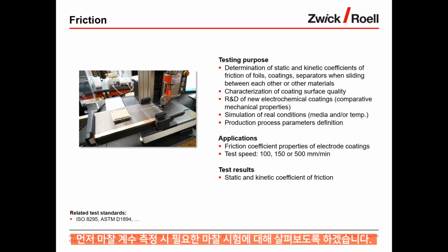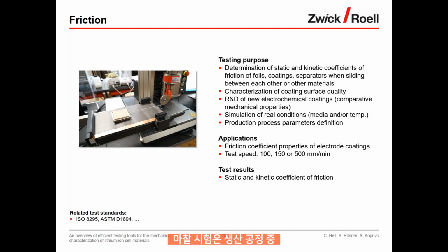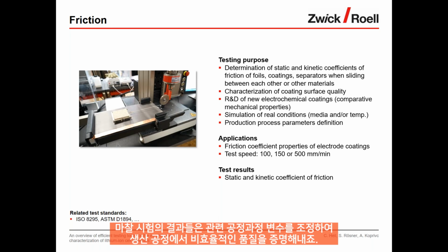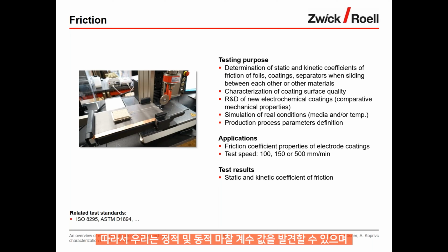Then we're looking at the friction test, which is used to determine the coefficient of friction, and it helps to characterize the interaction of the electrodes, coating, and separators during the production process. And the obtained results help to tweak relevant process parameters to improve quality and efficiency in the production process. So here we're looking at static and kinetic coefficient of friction values.